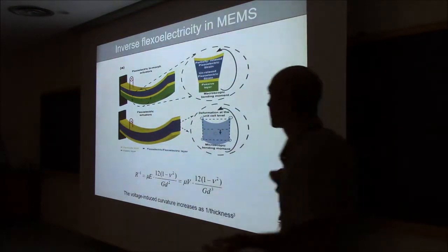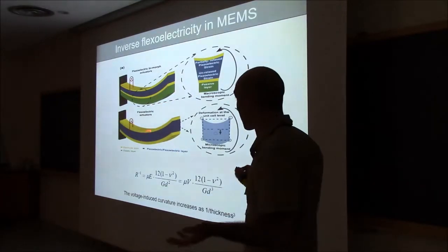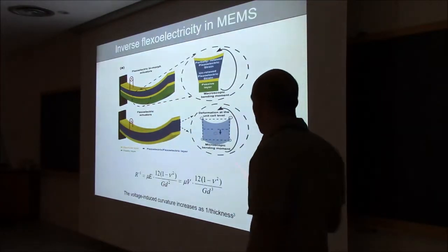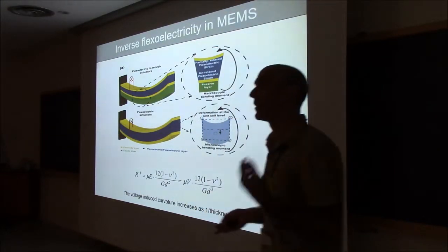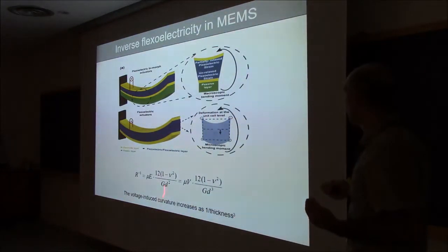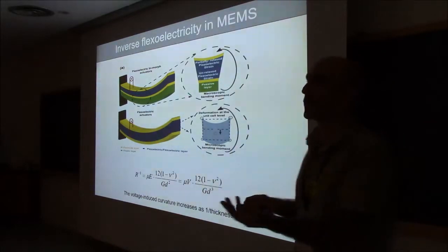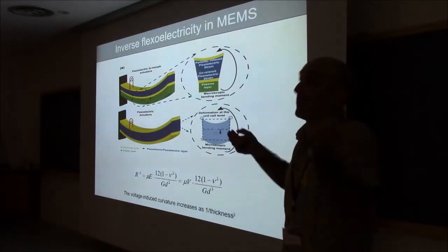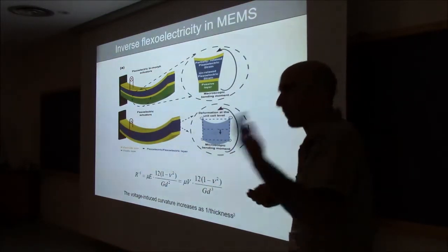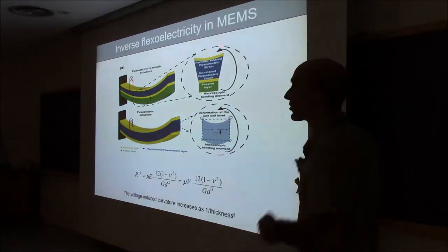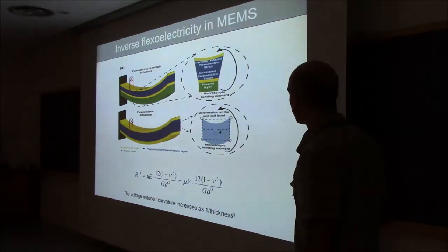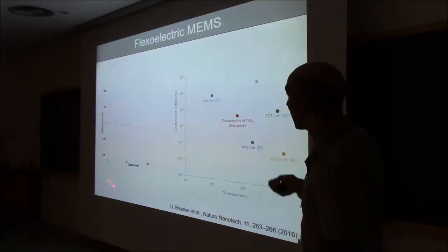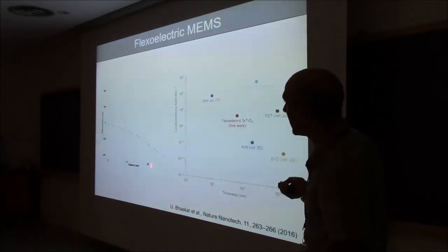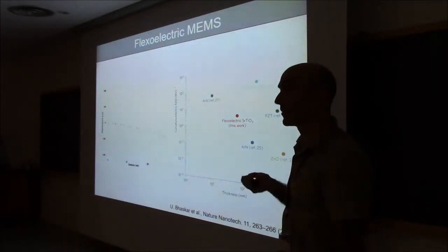If you have a flexoelectric, you don't need the passive layer, you just apply a voltage and the thing will bend. Remember, however, that how much it bends goes as 1 over the cube of the thickness, so this concept will only be really useful, not for normal actuators, but for MEMS, for things that are really thin. So micro electromechanical actuators or nano electromechanical actuators. If you do your thing micro or nano, the amount of bending that you can measure is big.